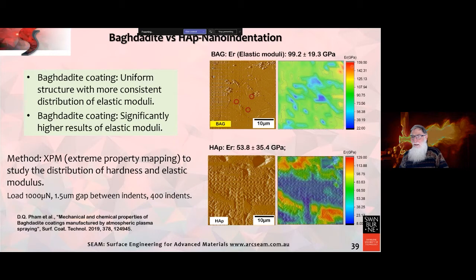of, for example, the modulus, the reduced modulus. And what we find for baghdadite is the modulus is 99 with a variation of plus or minus 19, whereas hydroxyapatite is about 54 and the variation is a lot greater. So the method we're using is extreme property mapping, and there's a series of papers that SEAM started publishing in 2019, and there are more recent ones coming out, and there will be others coming out over the coming year. But what we're able to do then is look at the mechanical properties in two dimensions.